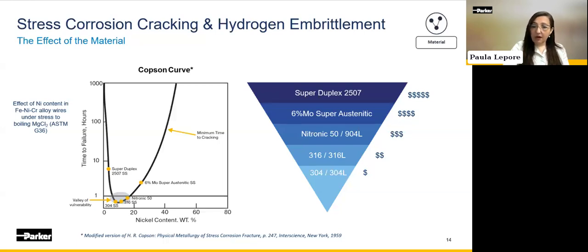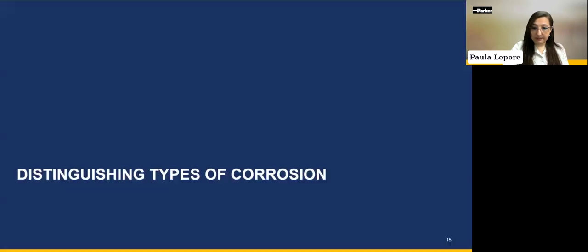it's only for numbers beyond 20%. This is the reason why we are forced to select higher alloys for critical applications, such as 6MO or super duplex, for example. All in all, the most important takeaway here is that adding a couple more percentage of nickel will only give you marginal improvement to stress corrosion cracking. Ultimately, chemistry is not everything when selecting your material for a specific application. Other factors need to be taken into consideration.